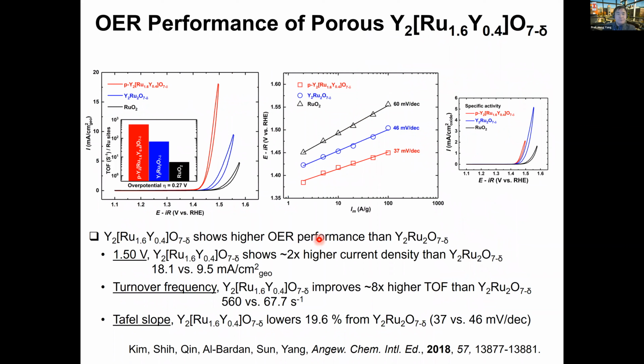With that, we could further enhance the performance. This is the geometric area, of course, benefiting from the opened-up pore structure for more contact. And if you look at the Tafel slopes, they also have some benefit from having this particular mixed B-site structure. At that time, we also looked at the specific activity based on the intrinsic oxide surface area. It turned out to be not that big. So we did not study super hard why the tuffle looks different, or whether we can utilize this aspect to further enhance the OER performance.